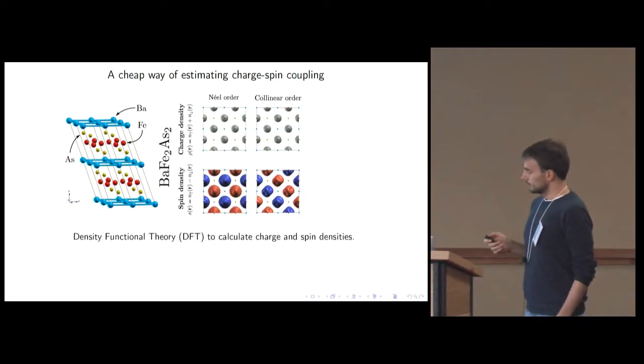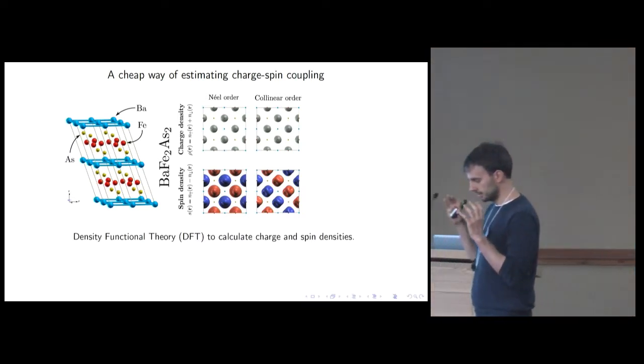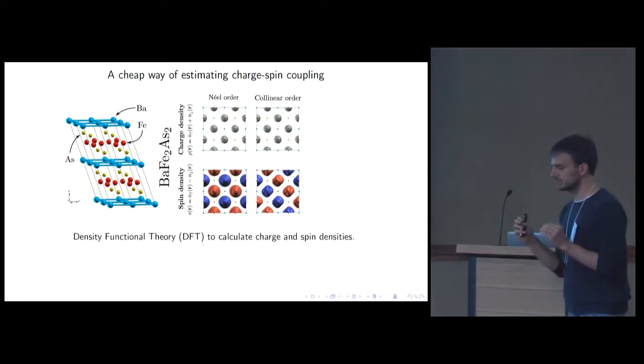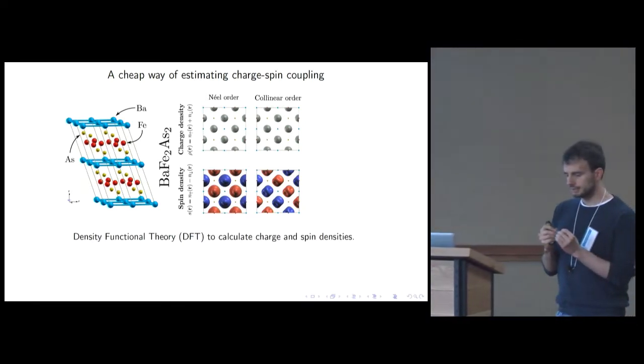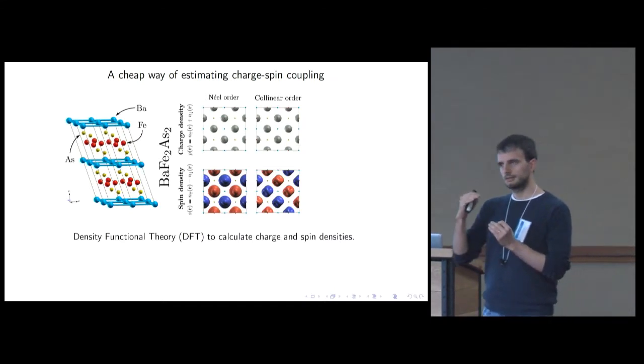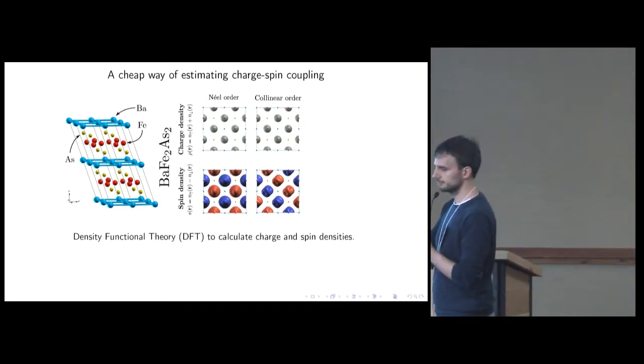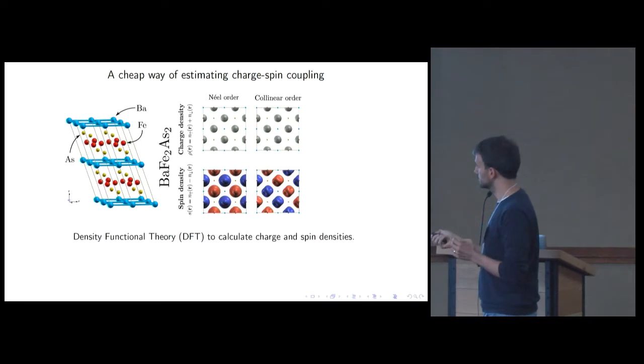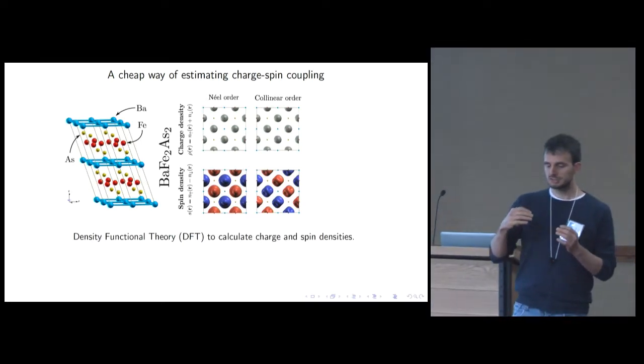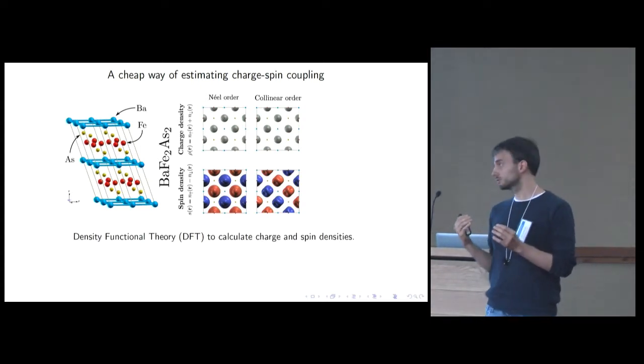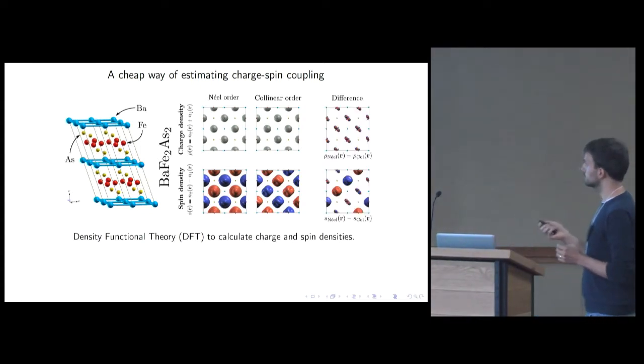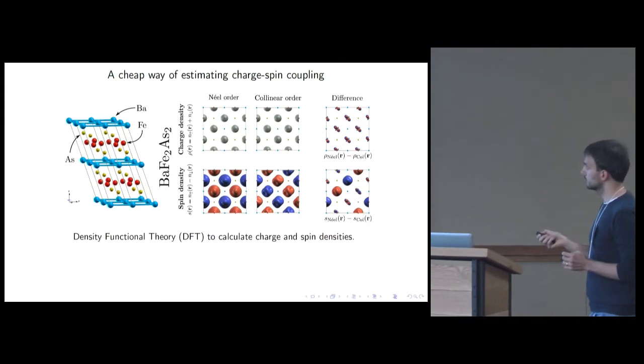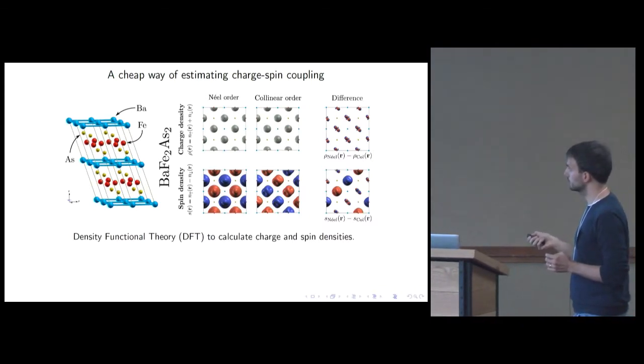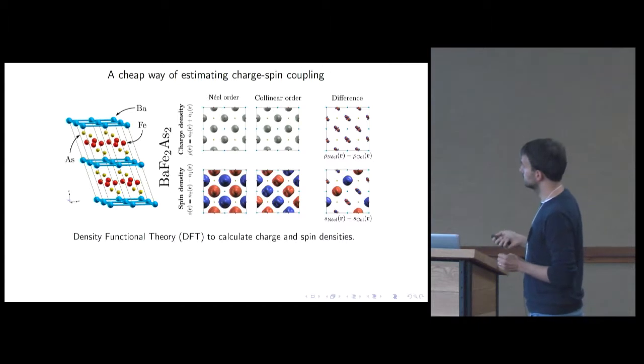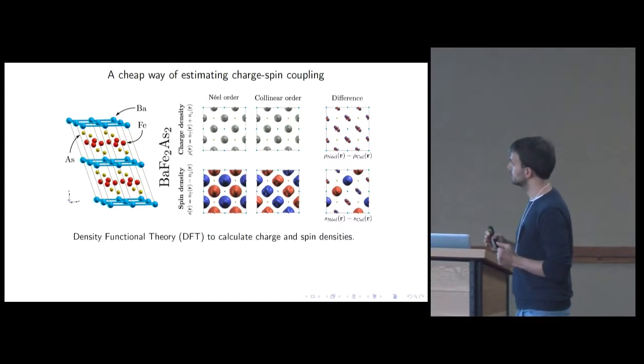So the idea of this probe is to essentially generate an excited state, an excited magnetic order. So this is the excited magnetic order, this is the ground state, and we see how much charge rearranges in comparison to the ground state. In order to do that, we just subtract the two. So we subtract these two, and we have this kind of density surfaces.